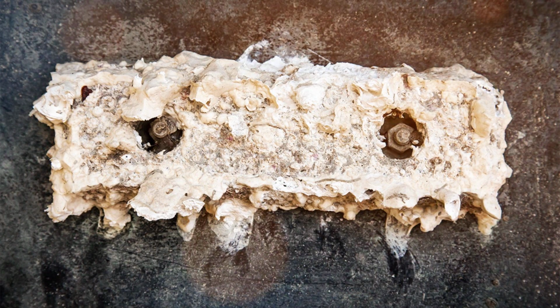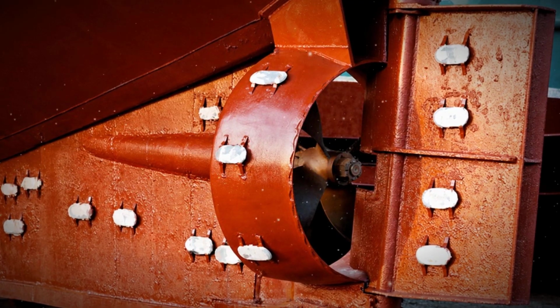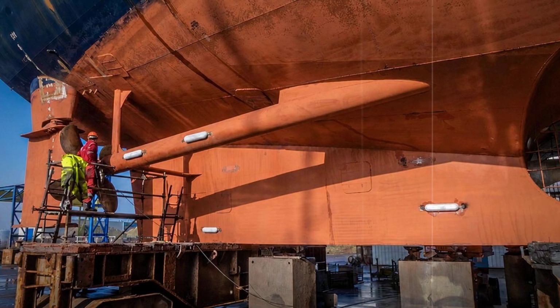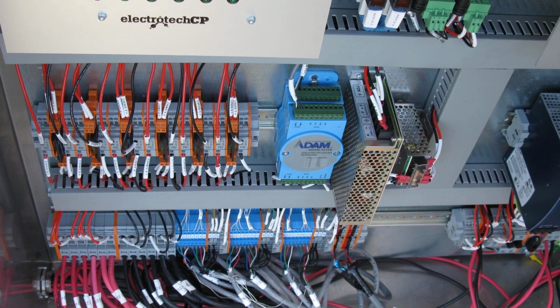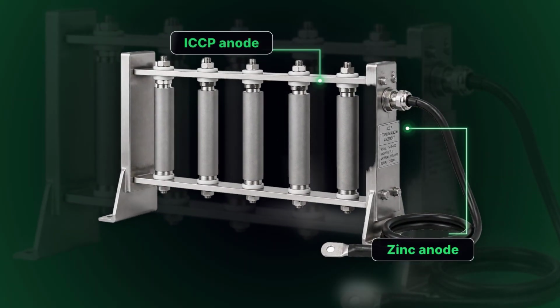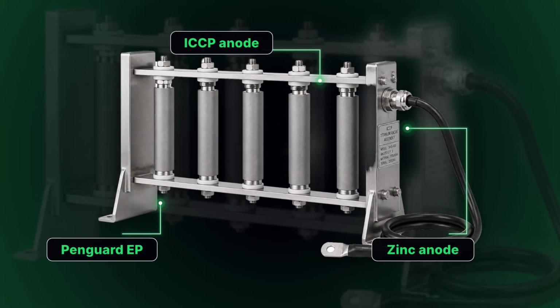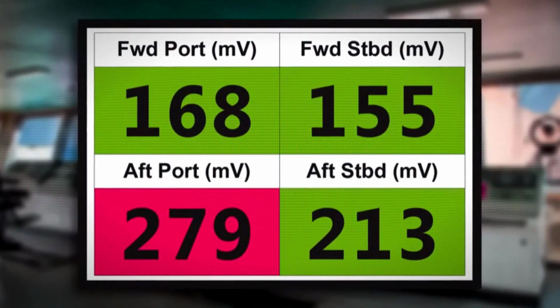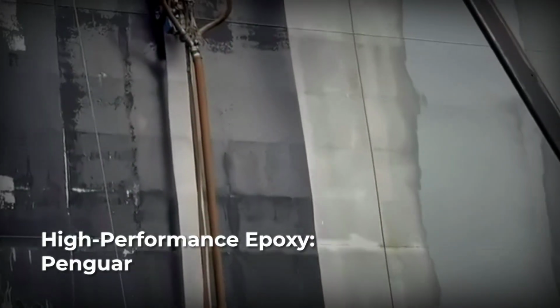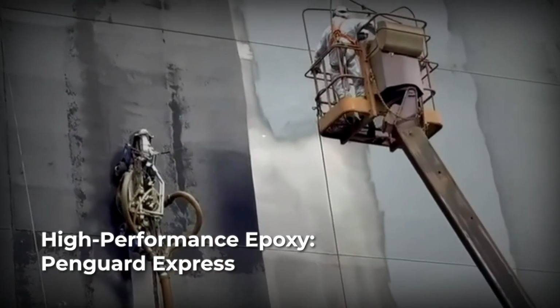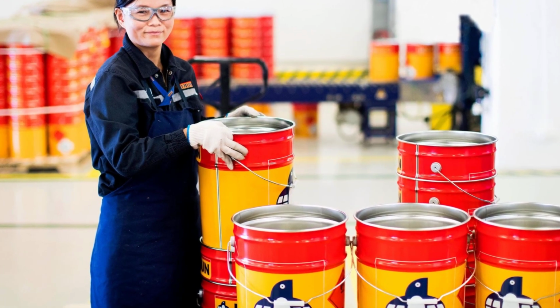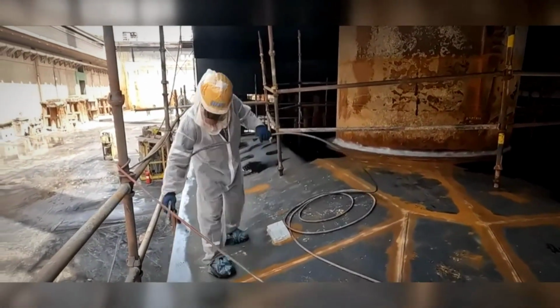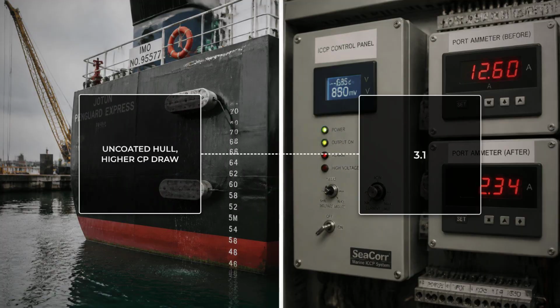The simplest approach uses sacrificial zinc or aluminum anodes, bolted directly to the stern frame, which dissolve over a 2 to 5 year cycle to protect the steel. For larger vessels, operators install impressed current cathodic protection, or ICCP. This system uses reference electrodes and titanium anodes to drive a controlled low-level direct current voltage through the wet hull, neutralizing galvanic currents. To support these electrochemical defenses, shipyards apply high-performance epoxy barrier coatings, like Jotun Penguard Express, to the hull plates immediately surrounding the stern frame. This localized shield blocks seawater contact and reduces the electrical demand on the anodes.